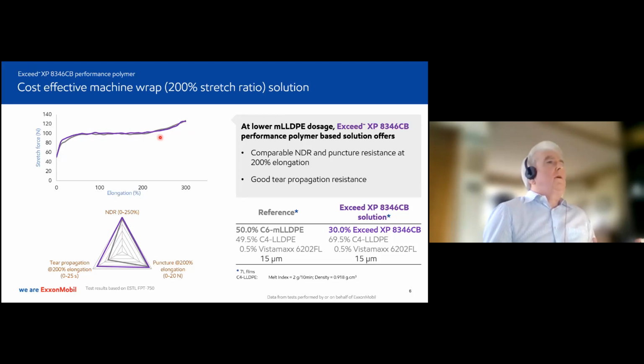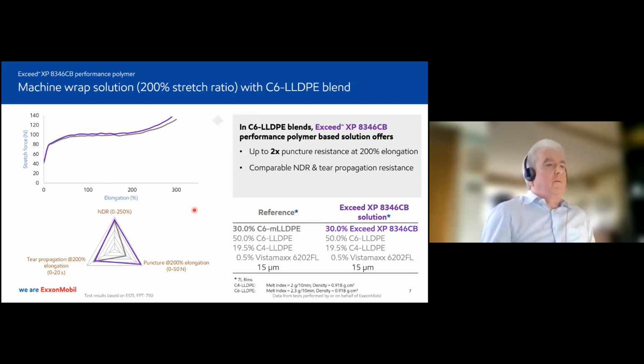Now here, what we're trying to show you is that by going to the reference structure, we're not losing out at all on NDR, okay? But we're gaining in terms of tear propagation resistance and still maintaining very good puncture at a much lower dosage, okay? Now we can take that one step further and say, well, what happens if we incorporated some Ziegler-Natta C6 into the structure? As you can see, in both cases we've got 50% in there. We've still got the 30% Exceed XP8346. And now we've got a significantly big boost in puncture resistance, as you can see.